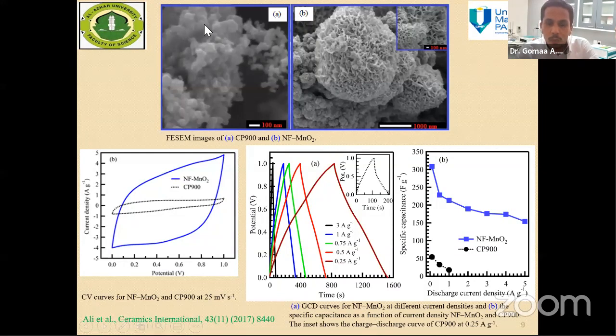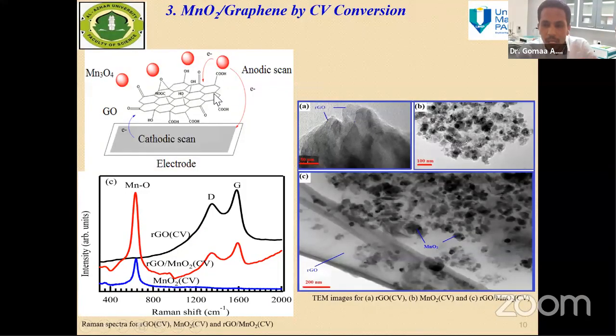One more example, we use the spent battery cathode powder, and at this time we combine with graphene. I mean, we synthesize not purely manganese oxide as in the previous two examples. In this case, we add graphene oxide, and simultaneously, the graphene oxide is reduced by applying cyclic voltammetry and converted into reduced graphene oxide, and successfully we obtained the nanocomposite structure of manganese oxide species distributed on the surface